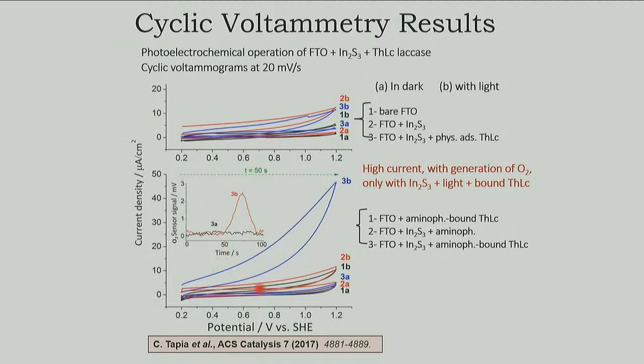Interestingly, in this experiment that takes 50 seconds to make this cyclic voltammetry, oxygen is not measured until we have a delay of 50 seconds. We assume this is because it has to go from the electrode surface to the sensor.